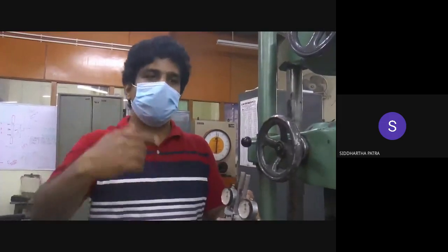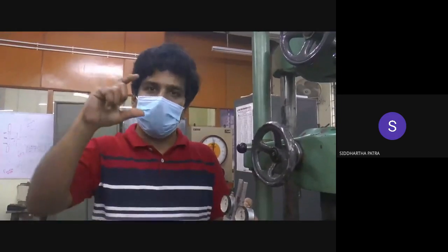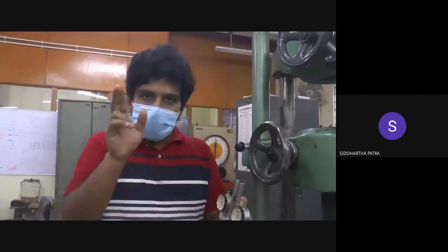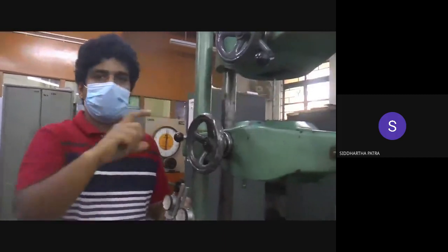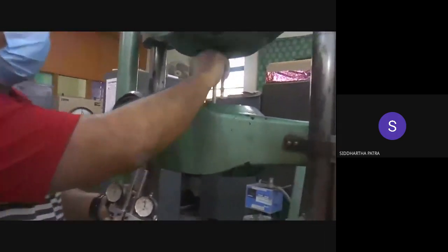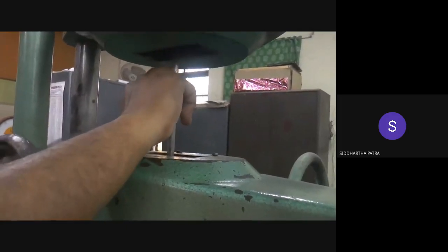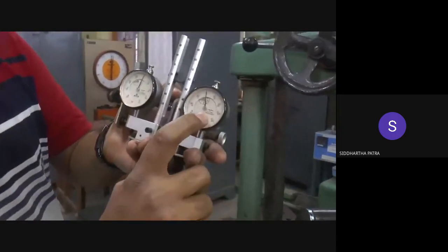from three-dimensional to one-dimensional stress state. And actually, the test that we are doing is suitable for uniaxial stress state. So we are doing an analysis with uniaxial stress state. To ensure uniaxial stress state happens in the region of the bar, we are supposed to take 1/3 of the total length. Now the total length is about 180 millimeters, around 160 to 180 millimeters. So we will be taking only 1/3 of that length in the middle of the rod, which would be around 60 millimeters, and that's why we attach the extensometer. The least count for the extensometer, you might notice, is 0.01 millimeter.